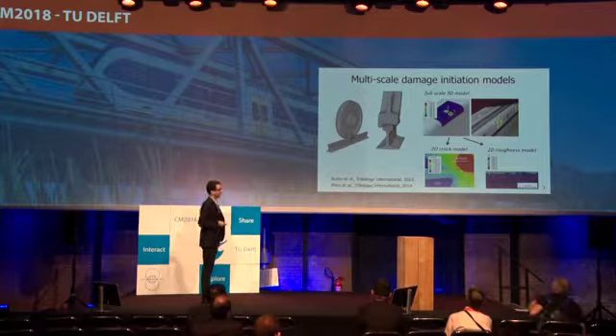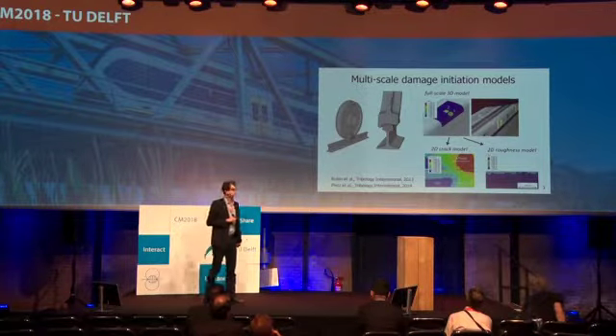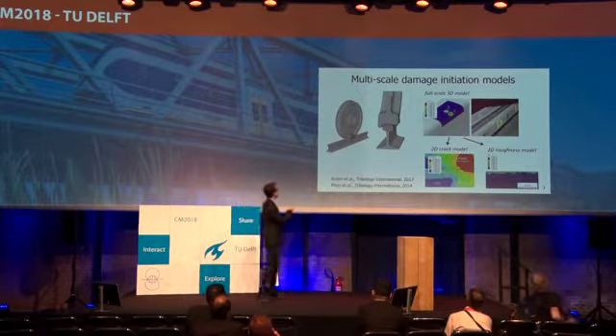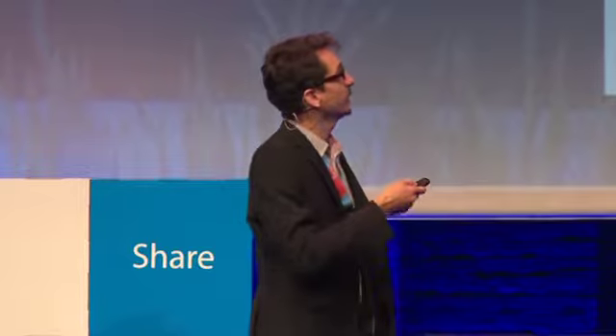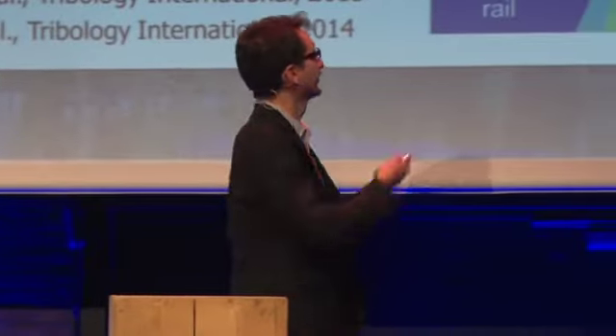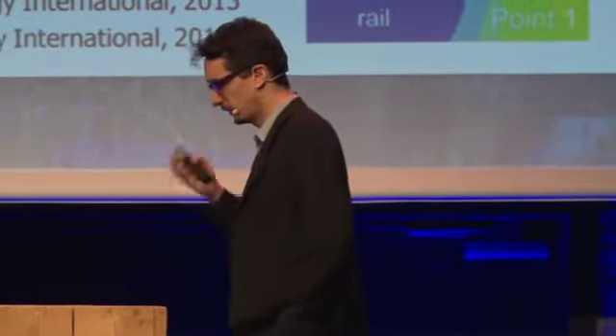That is some work that I showed 6 years ago in Chengdu. We took a full 3D model for the wheel rail test rig of the voestalpine, and we rolled over it. We saw where the contact patches would be, and then we thought about, good, we have now contact patches, they're non-Hertzian, there are maybe 2 of them, or could be more. What can we do with that? The thing is, we have some damage. How can we predict that?